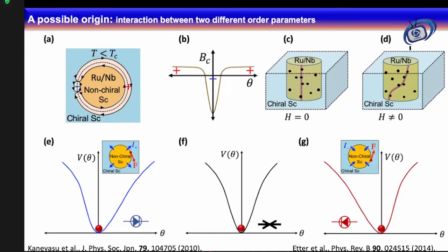And this vortex line develops spontaneously. It does not need any applied magnetic field, because a vortex state mainly occurs because of an applied magnetic field, but this one is spontaneous because of the frustration of two different superconducting order parameters. Then it can pin at some pinning sites, which could be some kind of defect there. If you do not apply any magnetic field, then it will be just a simple state there.